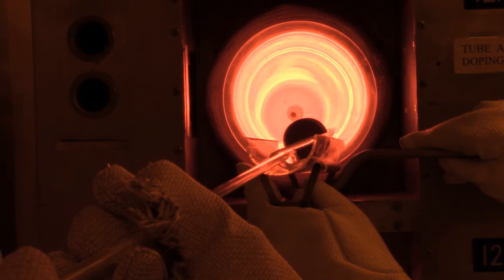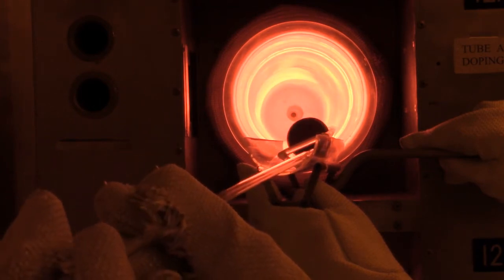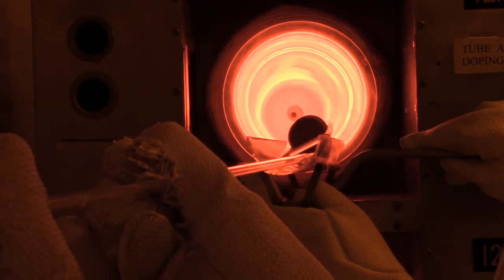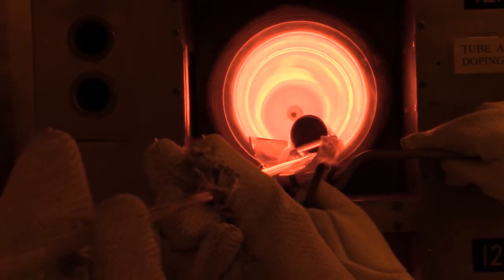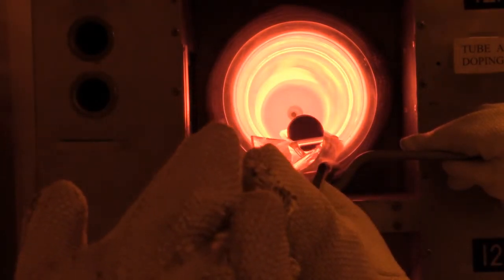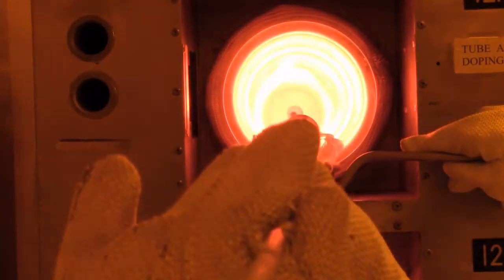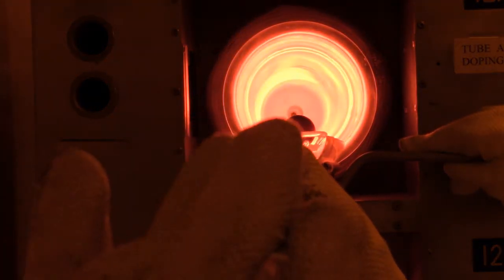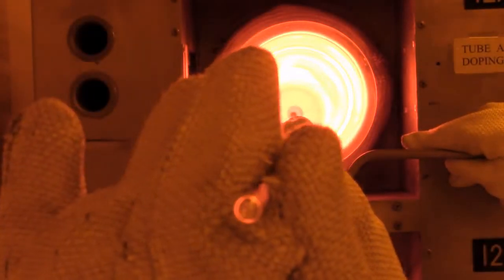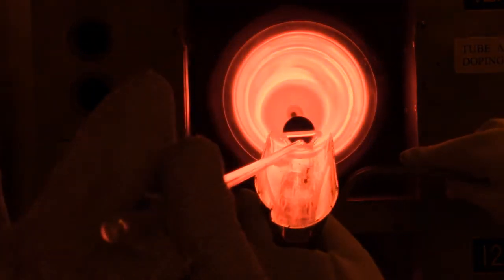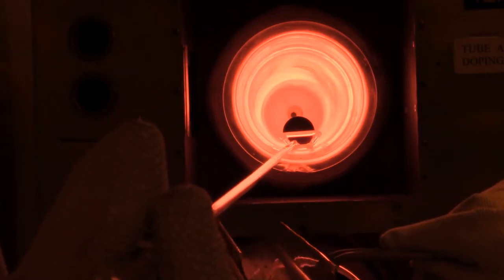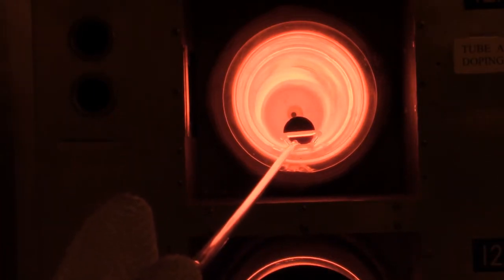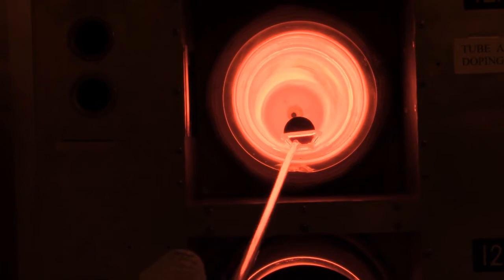Now that we have finished baking our spin-on dopant, we can go ahead and do the diffusion. This is done using Tube A with a mixture of 2 liters per minute nitrogen and 3/4 liters per minute of low flow oxygen. Check it out. We need to make sure that we push it 3/4 of the way in to start with the diffusion process, and we continue the diffusion process for 30 minutes.